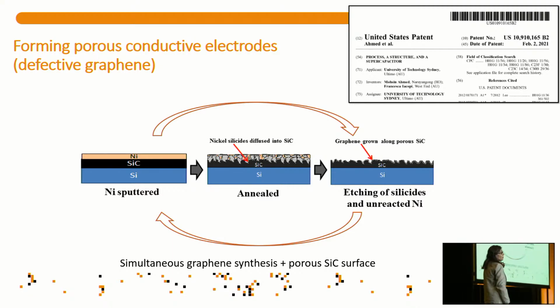We use a little bit of a tweak of that. In this case, actually, the problem is quite different from what I showed you before. Here, we want a very large surface area. That's what we want. We need the system to interact with the electrolyte as much as possible. So we want to make it really rough and effective. And how we do it, in this case, we only use nickel, and we just repeat until we have full coverage.